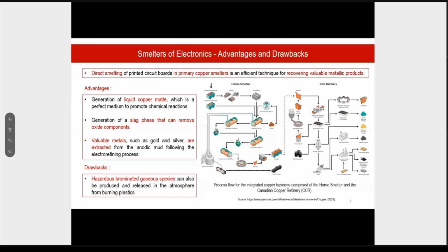We also generate a slag phase that can remove oxides like silica, which exists in very high concentration, over 30% of electronic boards. And we can recover valuable metals like gold, silver, platinum, and palladium using different processes like electrorefining. However, one of the biggest challenges with smelters is the toxic emissions released, as I mentioned, coming from plastics. Since plastic is one of the sources of energy used in the smelting process, breaking down the plastic by any thermal process generates these toxic emissions. However, smelters use very efficient scrubbing systems to reduce the impact of these gases on the environment.